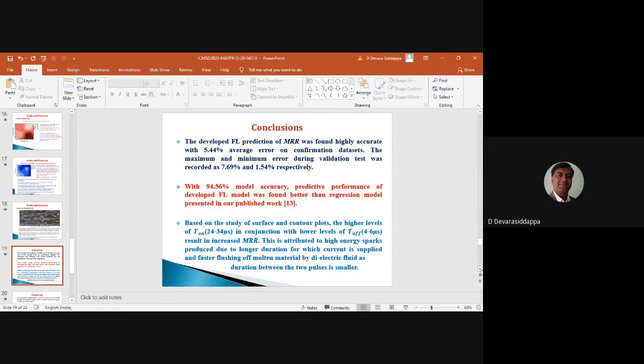So that is the discussion part, and I'd like to conclude my presentation with the following conclusions. The fuzzy logic prediction model developed for prediction of MRR in WEDM of titanium alloy was found accurate, with an average percentage error of 5.4%, a maximum error of 7.69 and a minimum error of 1.54. With model accuracy being close to 95%, the predictive performance of this model is also found better than the regression model of our published work.